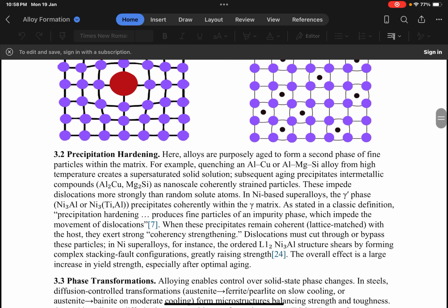Number 2 is precipitation hardening. Here alloys are purposely aged to form a second phase of fine particles within the matrix. For example, quenching an aluminium copper or aluminium magnesium silicon alloy from high temperature creates a supersaturated solid solution. Subsequent aging precipitates intermetallic compounds, aluminium copper and magnesium silicon, as nanoscale coherently strained particles. These impede dislocations more strongly than random solute atoms.